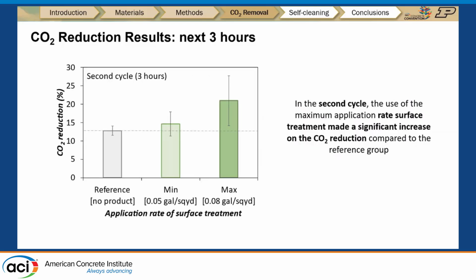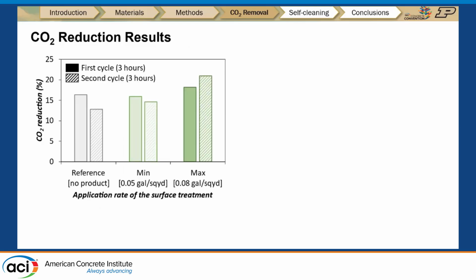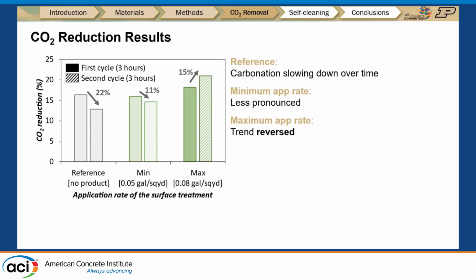So this is our result for the second cycle. You can see that in the second cycle, the use of the maximum application rate surface treatment made a significant increase in the carbon dioxide reduction compared to the reference group. And if we put these 2 cycles together, we can see that in the reference group, the carbon dioxide reduction percentage is actually slowing down.